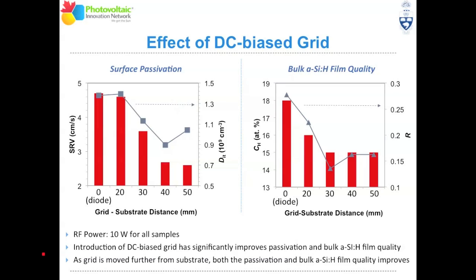So what we found was, when we first took the grid out, so that's in the figure here showing 0 millimeter grid to substrate distance. That's without a grid. That's just a typical diode configuration. We got pretty good properties. We got a fairly low surface recombination velocity, and we got decent bulk film properties in terms of the hydrogen content and the microstructure parameter.